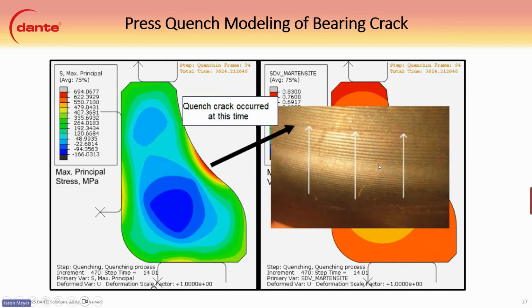So there's a little more exploded view in the timestep here. Again, we have the crack, and we see the high tensile stresses. In the core here, you can see it is a little bit in compression. That's because the martensite is transforming here, and it's basically pushing out. You can imagine arrows pointing out in all directions here, and it pushing out like that. The only way it can go is out this way, and it opens up the bearing race. It causes high tension in the martensite phase.